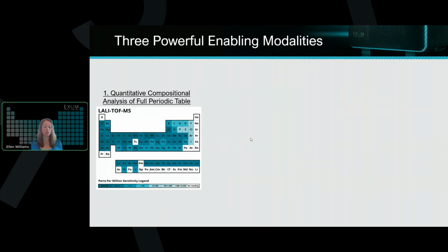This image that you're seeing here is a graphical representation of the technique's detection limits, where the darker blues are down to the sub parts per million level, and even these lighter blues are in the parts per million range for some of these low mass elements that can be traditionally very challenging to measure with X-ray or other spectroscopy techniques. So you can see every element that is colored there we can detect, and the different colors represent a range of detection limits from sub parts per million to low parts per million.